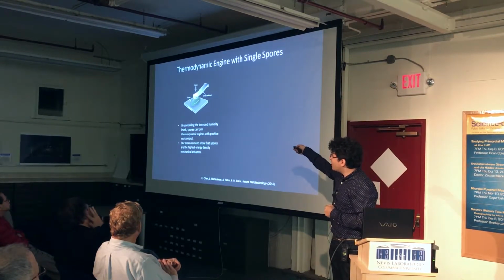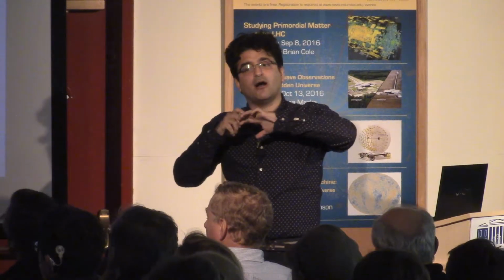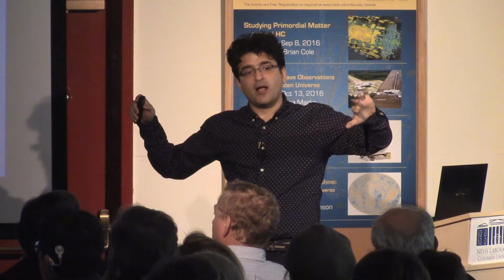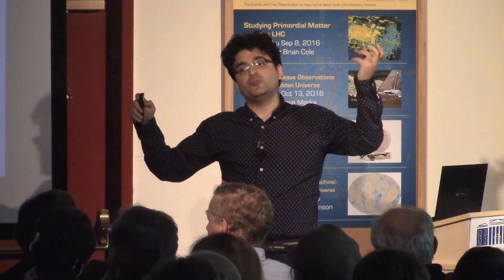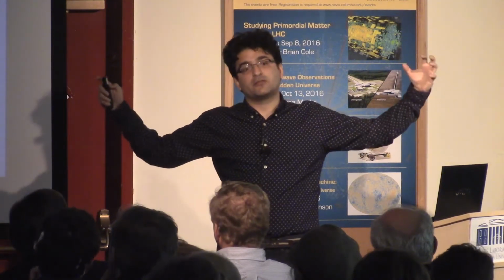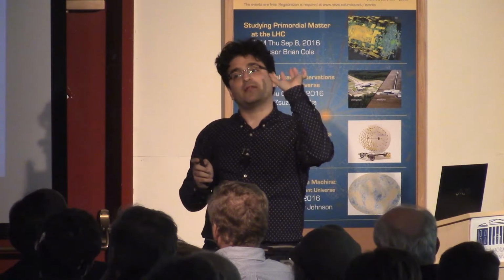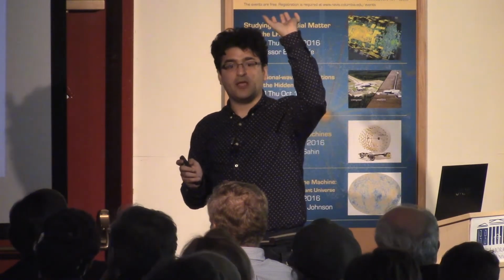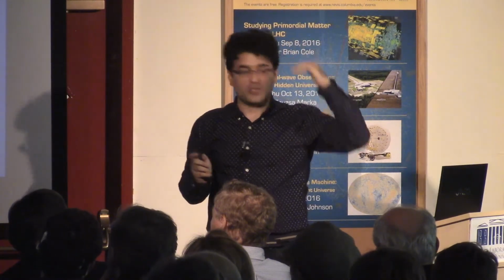If we use this diving board-like cantilever and press on it, we can push out some water. And if this is already in a dry condition and then you increase humidity, the spore will like to take water, and it will push that cantilever up. It will do work. It will lift something that's already pushing on it really hard.